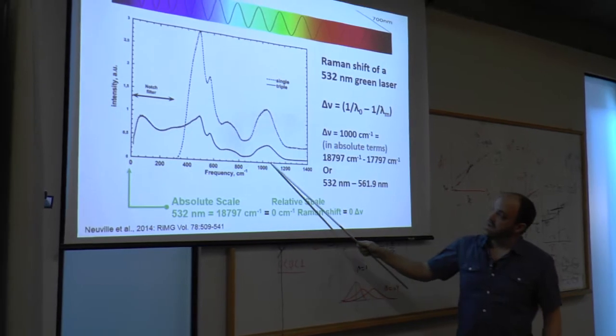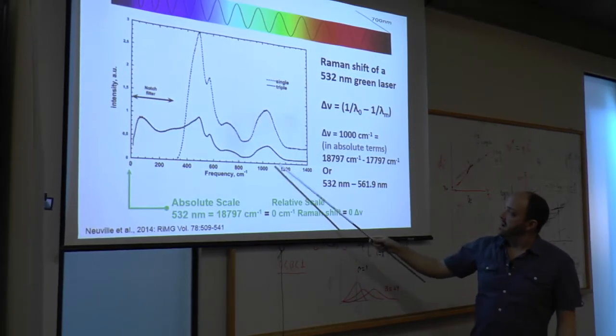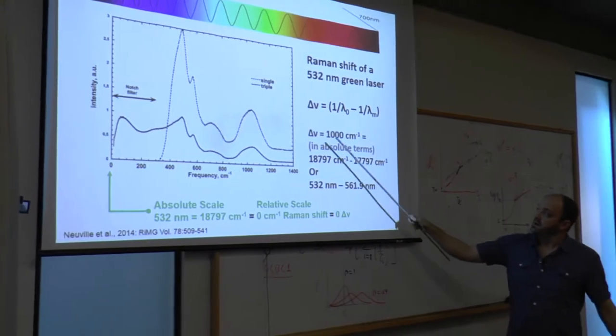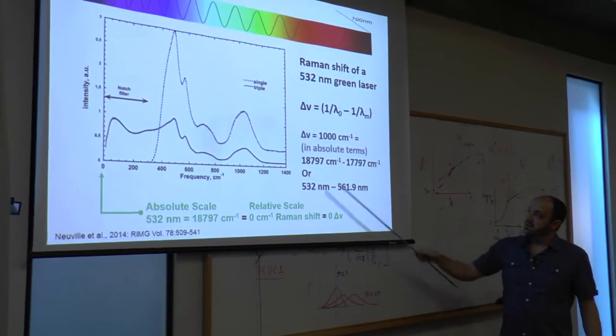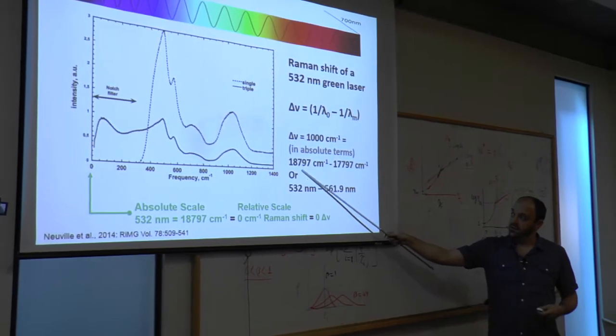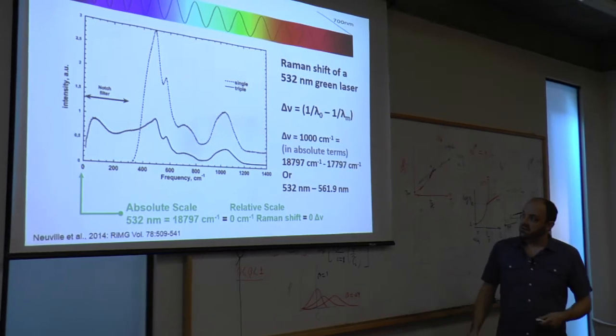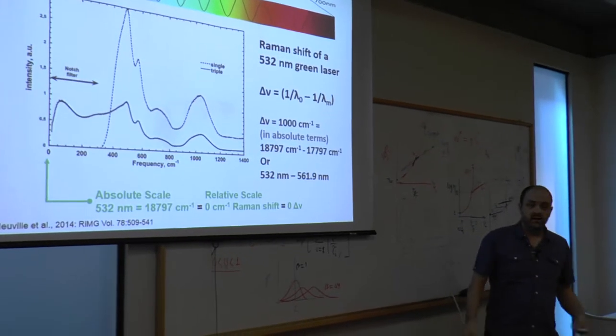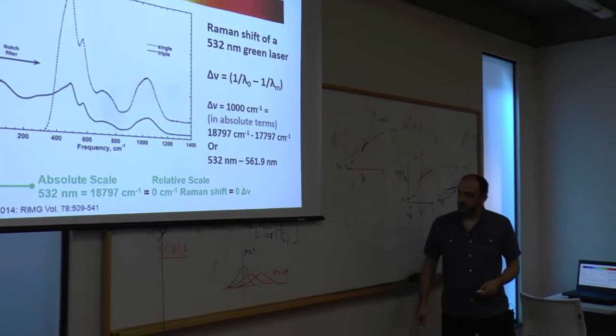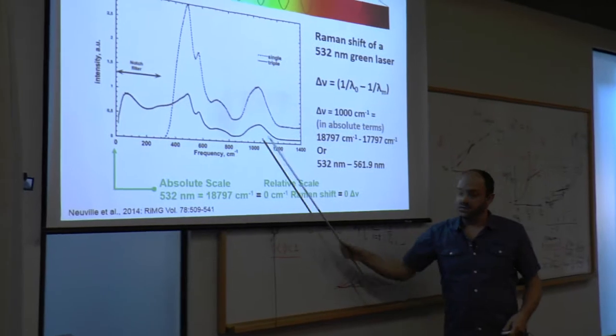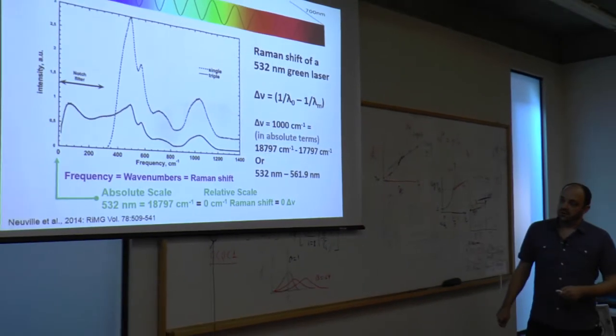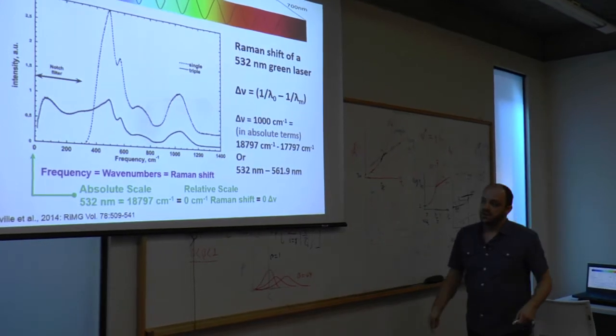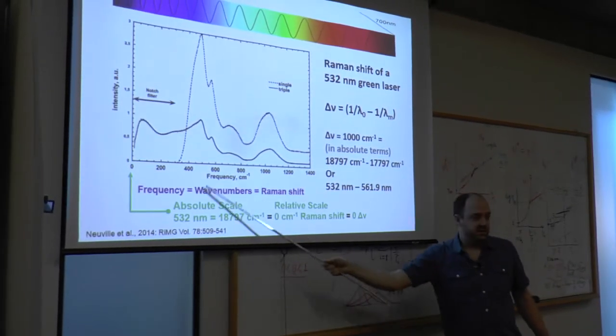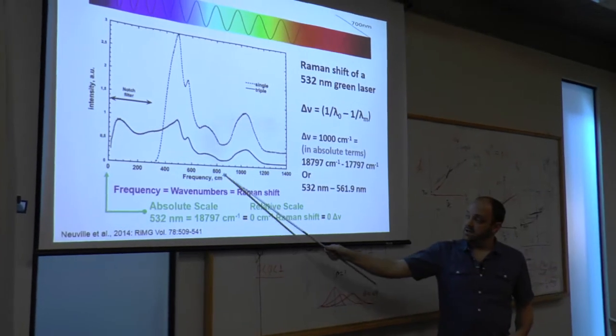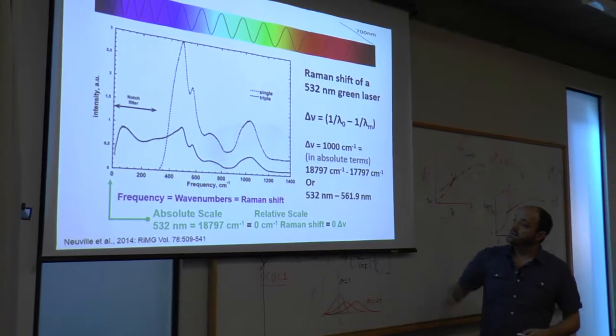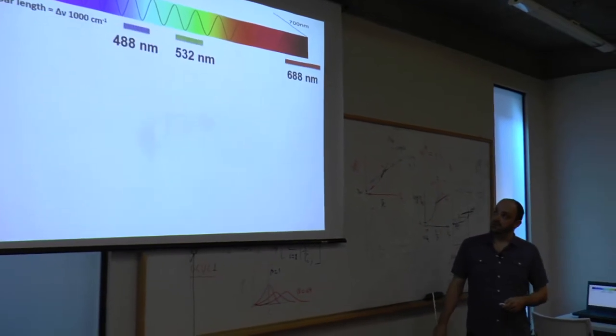So if we go over in this example, this is the spectra of pure silica, and we look at this band around 1,000 wave numbers. In absolute terms, 1,000 wave numbers is 18,797 minus 17,797 inverse centimeters, and you can convert that to wavelength. It's a shift of about 30 nanometers. But in relative terms, it's still 1,000 wave numbers. So throughout the presentation, throughout the papers, you'll see the frequency or the Raman shift or wave numbers, it's all the same. It refers to this inverse centimeters, and it's all relative to the excitation wavelength you use.